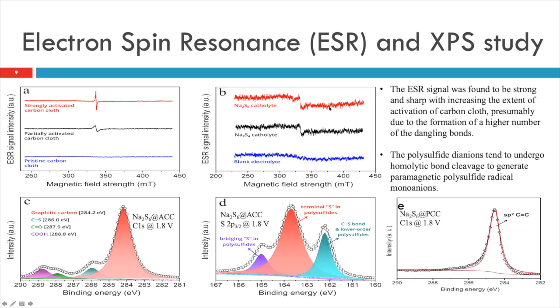This spectrum is not very good because it is carbon fiber, and on top of the carbon fiber this electrolyte catholyte was there. That's the reason we did not observe a very strong signal. And what we are saying here is that when this radical is formed, S3 couples with it, making the polysulfide absorb on the surface and also catalyzing the reactions, because we see that the sluggishness of the reaction is not there.